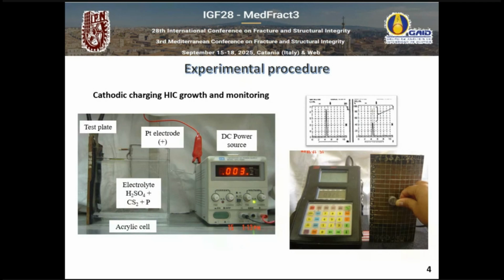Okay, so in this setup, we put the specially formulated electrolyte. We use an inert, in this case, platinum anode. And by means of ultrasonic mapping, we are able to record the location and the growth of these cracks.